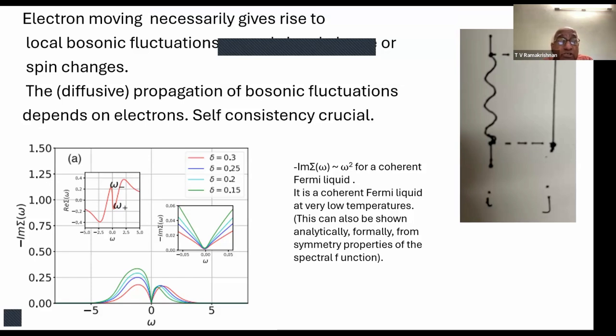For example, this inset shows the plot of the imaginary part of the self-energy as a function of frequency for different dopings. You can see that at extremely low frequencies, it is parabolic, proportional to omega squared, but then very quickly it becomes linear. Here we have also shown the real part of the self-energy, which ought to be linear, which it is if it's a quasi-particle. So the behavior of Im sigma as omega squared, and of Re sigma as omega for small omega, is a signature that you have quasi-particles. And you actually do have quasi-particles at extremely low temperatures and extremely low frequencies.